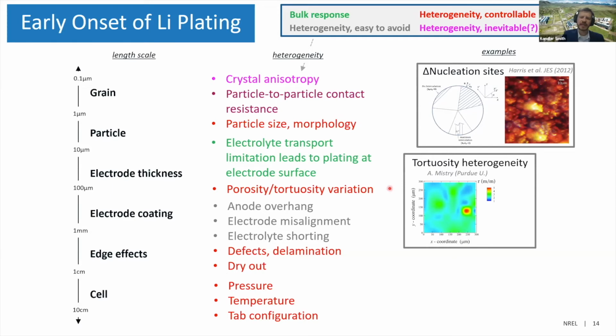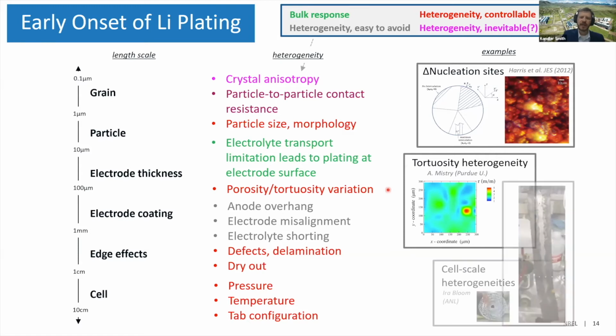And we feel that this is leading to preferential areas of lithium plating early on. We've done some modeling together with Purdue University. Dean Wheeler from Brigham Young University is part of the project now, and he has some methods to characterize the tortuosity locally across electrodes. So we'll be looking to validate the models for that. And then we haven't yet spanned up to these length scales, but at the cell level, there's additional heterogeneities. And these are some images from Ira Bloom at Argonne National Labs. It's an unrolled jelly roll. You can see that the preferential plating has occurred, I believe, at the center of the jelly roll, as well as the center of the height of the electrode.